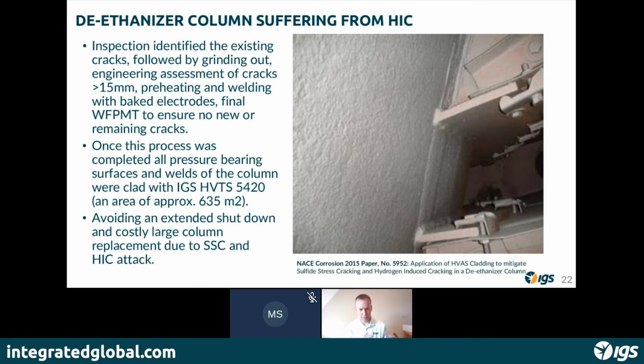Prior to us doing the thermal spray application, which is the corrosion barrier, the client first of all had to ensure that all the cracks that were present had been terminated. So he did his mechanical work on any cracks that were deemed to be at risk, grinding them out and doing re-welding and then localized heat treatment. Once that was complete, we could then come in and do the surface preparation and the application of the thermal spray system.